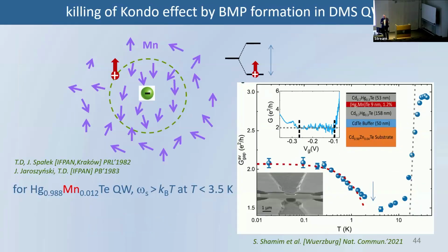But again, we come back to doping with magnetic impurities. This was mercury telluride without magnetic impurities. What happens if you now add to the material, to mercury telluride, these magnetic impurities? As we mentioned, there is bound magnetic polaron formation, and some of you may know that if your spin is split by external magnetic field or exchange interaction, this Kondo effect is very strongly reduced. Kondo effect is not any more efficient.